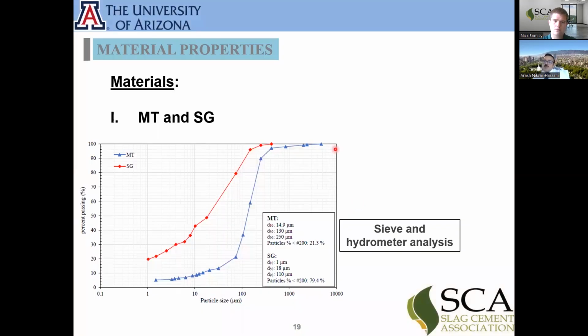So first, let's talk a little bit about the material itself. The materials we are using here are mine tailings and slag. If you check their particle size distribution, we see that they are pretty fine materials. For the slag, we didn't use any commercial slag available from the industry. We got the slag tailings, like the stones, from the mining landfills, and we powdered them in the lab. So there is no other process applied to the slag powder. You see the material is mostly less than 100 microns in size.